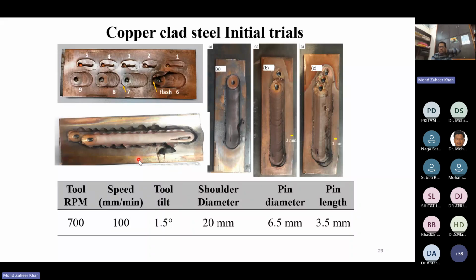Tool RPM, as I told you, 1000 was giving excessive heat. So 700 RPM, 100 millimeter per minute, 1.5 degree tool tilt, 20 mm shoulder diameter, 6.5 mm pin diameter, and pin length of 3.5 mm worked well, because the thickness of the clad layer that we have deposited was 3 mm.